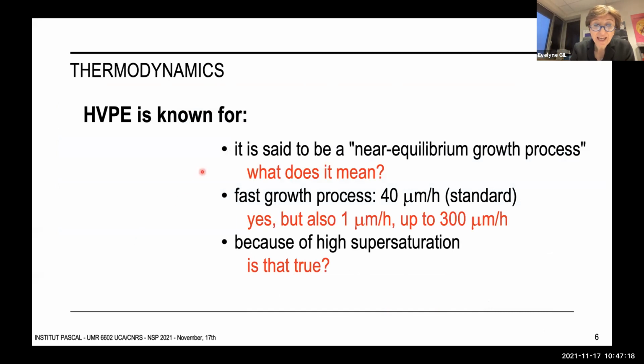HVPE is commonly known as a near equilibrium growth process, and this needs to be clarified. It is known for its fast growth property, but HVPE is also a process that allows to vary the growth rate from 1 micron per hour up to 300 microns per hour.